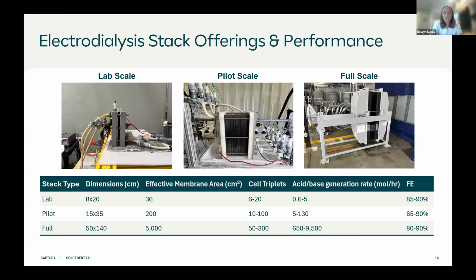We then have a pilot scale, which operates at our pilot facility in Alta Sea that allows us to test membranes on our actual ocean water system at a slightly larger scale. And then finally, we've just finished commissioning our full scale stack. This is being tested in our Pasadena facility and has dimensions of 50 by 140 centimeters. That's this final image here. The image here, I believe, has 100 cell triplets in there. And this is what we'll actually use in full direct ocean capture systems. We would take this unit you see here and repeat this unit as many times as needed, depending on the size of the ocean capture system.